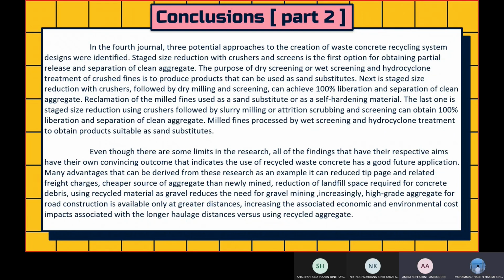In the fourth journal, 3 potential approaches to the creation of waste concrete recycling system designs were identified. Staged size reduction with crushers and screens is the first option for obtaining partial release and separation of clean aggregate. The purpose of dry screening or wet screening and hydrocyclone treatment of crushed fines is to produce products that can be used as sand substitutes. Next is staged size reduction with crushers, followed by dry milling and screening, which can achieve 100% liberation and separation of clean aggregate. Reclamation of the milled fines is used as a sand substitute or as a self-hardening material.